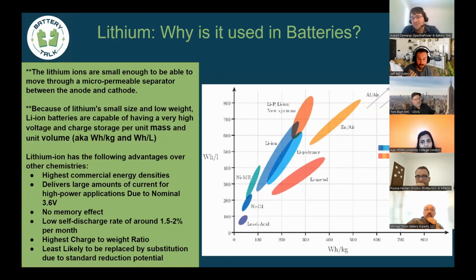Basically, why we're using it is mainly because of its performance characteristics, guys. So basically, if you compare it to nickel metal hydride, nickel cadmium, lead acid, you'll see that lithium ion in general, or lithium polymer, or the lithium metal batteries, all significantly exceed them from a watt hours per liter and watt hours per kg point of view. But that's not the only thing really, right?